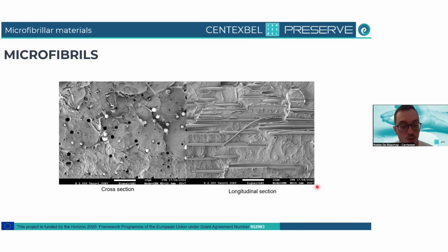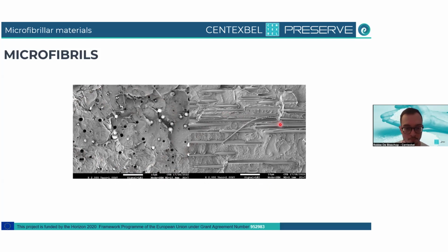And here I can show you two SEM images of a microfibrillar reinforced material. On the left-hand side, we have the cross-section. On the cross-section, we see all these little droplets that are very well dispersed and well distributed in the material. And then we look at the longitudinal section, in the extrusion direction of the extrusion process, and there we can see that we have very nice, good-looking fibrils of this material.